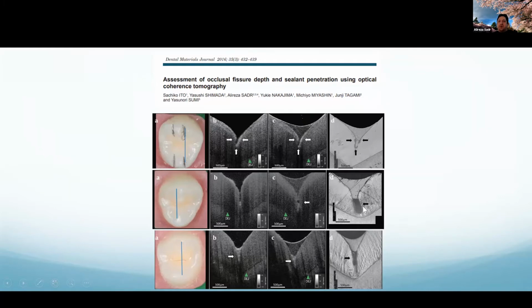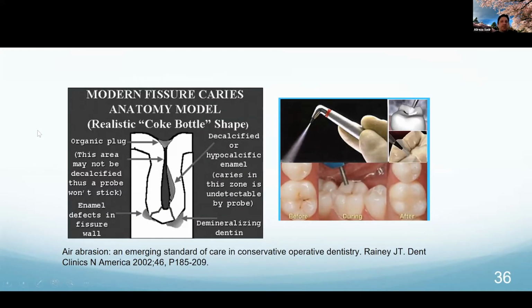But this one is in vitro. So when you look at the actual microscopical image, it is kind of disappointing. It is really disappointing, right? So whether it's glass ionomer sealant or resin-based sealant, it's really difficult to get a complete penetration, right? I want to refer to Dr. Rainey's publication here. Many years ago, he talked about this Coke bottle shape and the actual anatomy of the fissure, the way we thought it is and the way in reality it is. And I was kind of blown away when we did this OCT study because I could see these images published maybe 10, 15 or 20 years before we really came up with that clinical evaluation of thousands of fissures anatomy and finding that this is the more predominant type of fissure, right?